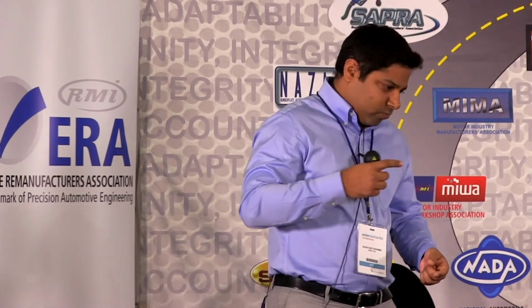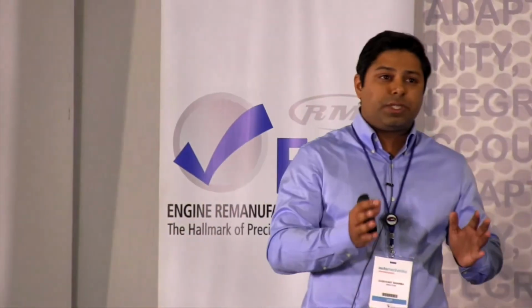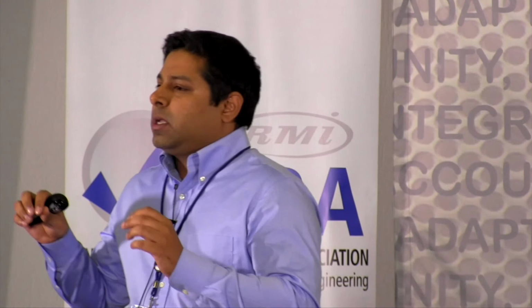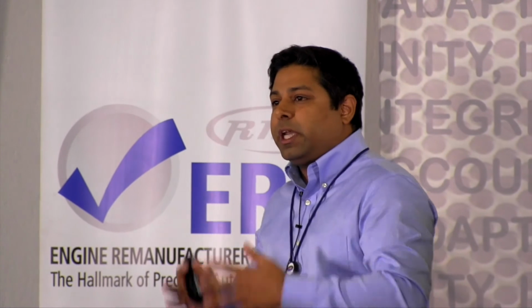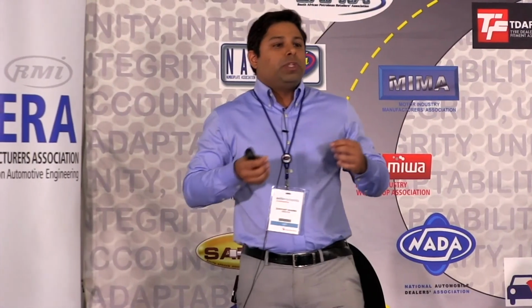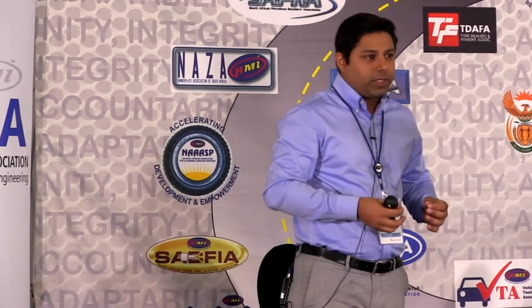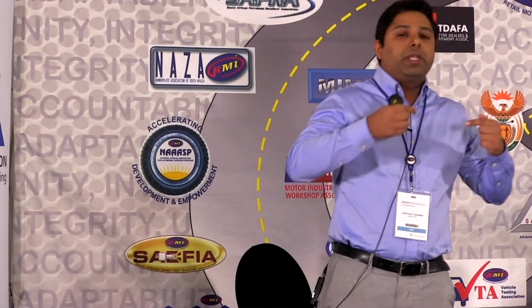Especially because cylinder liners, for purposes of doing it at the right price, you also need to mix a certain amount of cast iron scrap. So if you don't select this scrap carefully, there will be a large variation in the ferroalloys present in that scrap from batch to batch, and then you cannot make a consistent material in your foundry. So this is why it is very important to work with manufacturers who in turn choose their sources of raw materials very carefully.